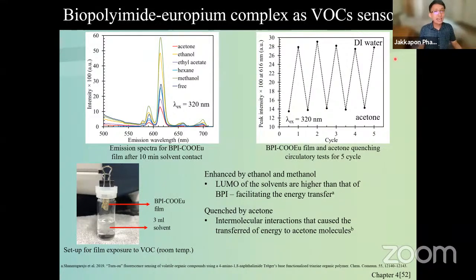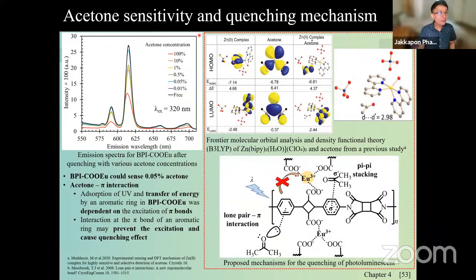So here are the VOC sensors. I have to say that the sensitivity of quenching is very important here, because it can sense 0.05% acetone, and it can sense different percentages of acetone here. So it depends on the sensitivity. As the acetone goes up, the intensity goes down, and this is trying to explain the sensitivity to acetone.